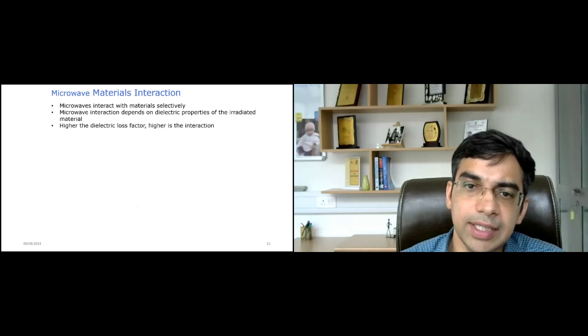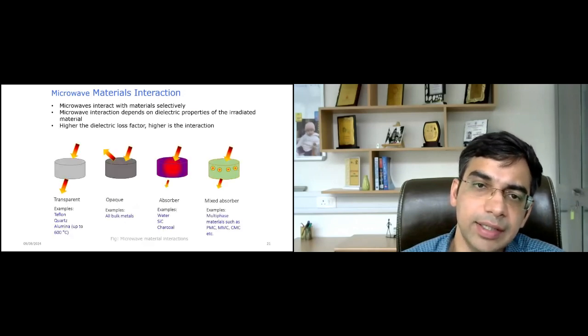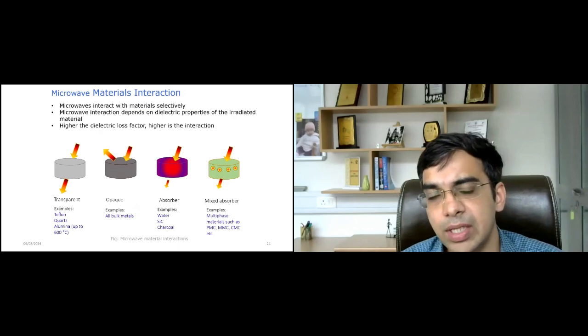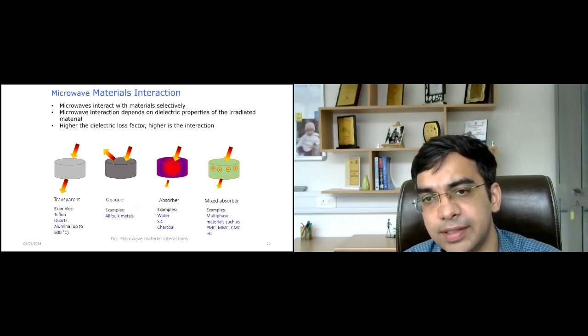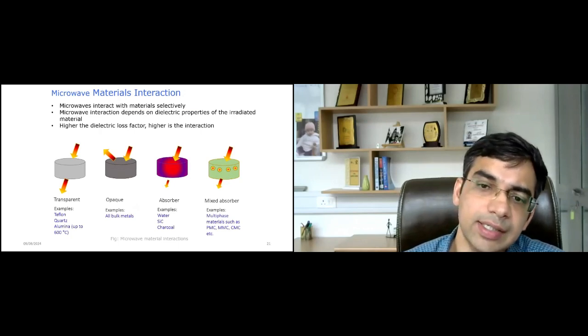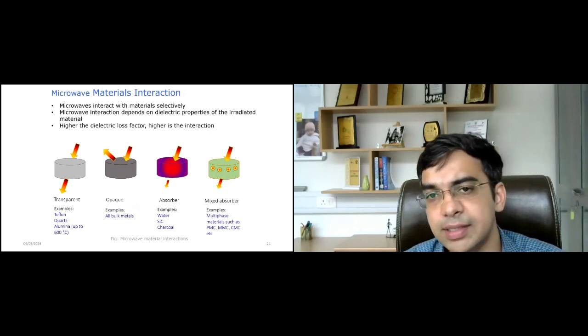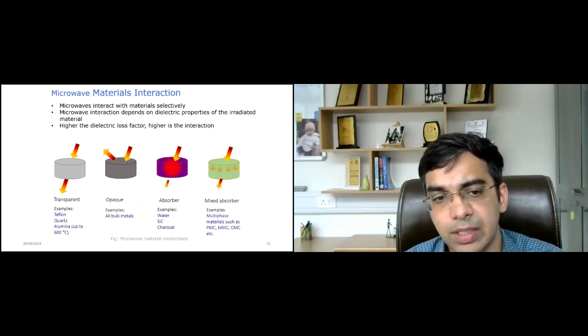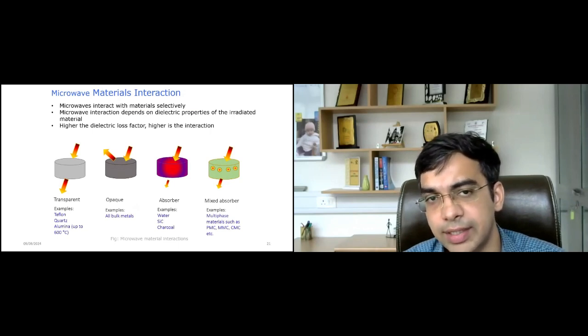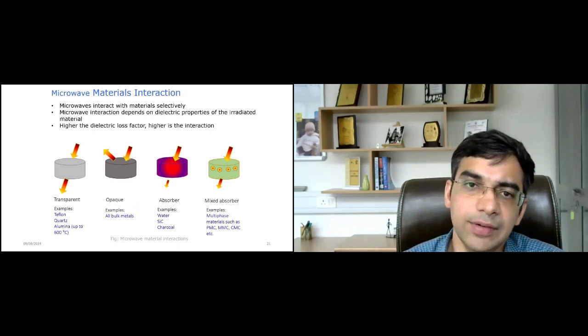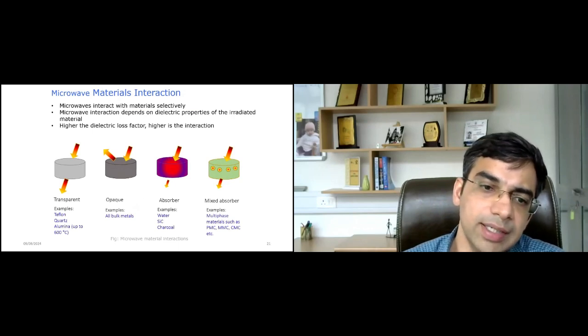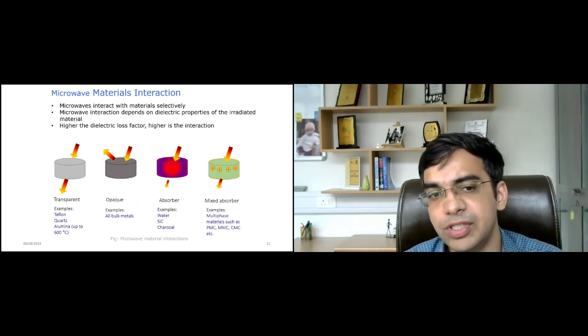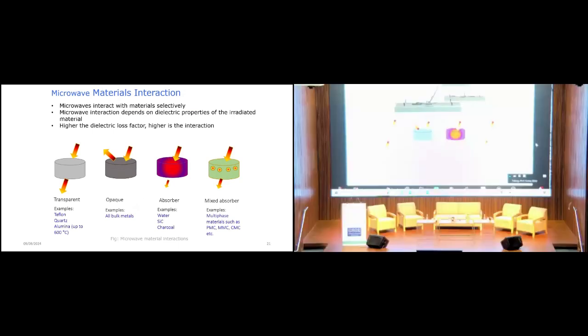So, as I mentioned earlier, microwaves are very selective to the materials they interact with. This selectivity comes from the dielectric response or dielectric properties of the material. Some materials have a very high dielectric loss factor, so in that case, the interaction is much higher. In other materials, the dielectric loss factor may be much less. Based on this interaction of the microwaves with different materials, materials can be classified in 4 types, which includes transparent materials, opaque materials, absorbing materials, and mixed absorbers.